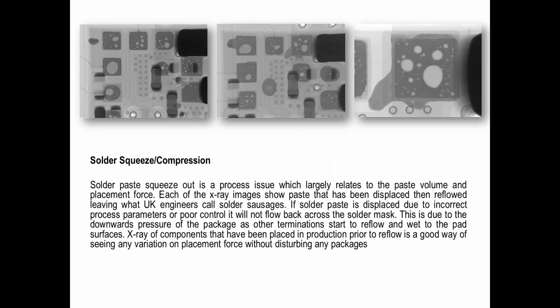Now if I look at here, this is a beautiful example of a very bad product, but what you're looking at here is somebody who really had no control of the downstop. So they displaced paste away from the pads, they reflowed, and we've got what some engineers, certainly in the UK, refer to as solder sausages. I don't know who dreams up these names, but you know, that's clearly what we've got. We've got solder protruding between terminations. We've obviously got some large voids. So take care with any area array LGA type package that you've got control of the process, you've got a consistent volume of solder paste, and you don't squash it when you're placing components on to the surface of the printed circuit board.